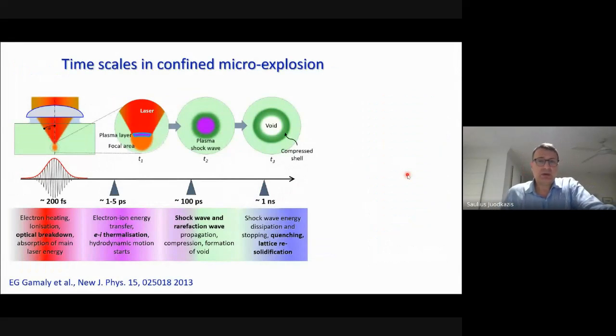So what is happening with material when we deliver ultrashort pulses? Let's have a look at transparent material, because this is where femtosecond laser machining really stands out. If we are focusing to a focal spot, we know what to expect. But when intensity is high, we are actually reaching the breakdown condition. We are creating a plasma excited state with free electrons. This plasma state is a kind of metallic absorbing material, which is created following the pulse duration. So it's usually happening on short times. And then the material is modified.